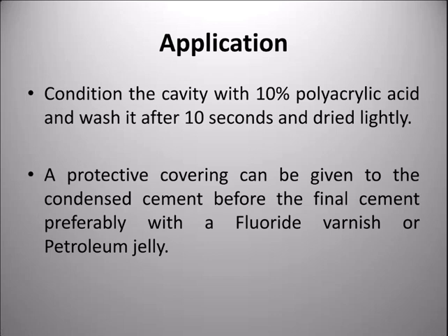To prevent these two things, the washing away of matrix-forming ions by saliva and the evaporation of the labile water, we apply a protective coating like petroleum jelly or a fluoride varnish. That's why. So you should always know that this is for protection and for proper initial setting to happen. Okay, understood, guys? Do you want me to repeat it? That's why we give a protective coating like a fluoride varnish or petroleum jelly. If it is light activated, there is no need for this. I'm talking about when it is chemically activated or self cure. Okay, understood?